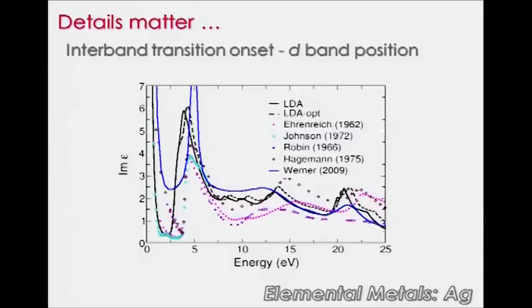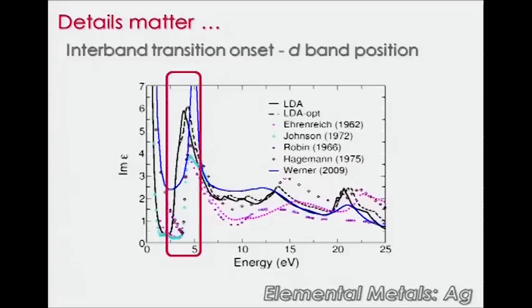I mean, you see from this mess out here how important it is to have reliable data. Otherwise, we cannot really compare our theoretical results and evaluate our theories. If we don't know what the real experimental data are, we don't know how good the theory is. But in any case, even if we're much happier now with the new data, which gives us at least the same peaks, the same structure in most of the cases, there's of course room for improvement. So details matter, and in particular here in the absorption onset, and this has simply to do with the fact that DFT doesn't capture the right position of the d-bands.